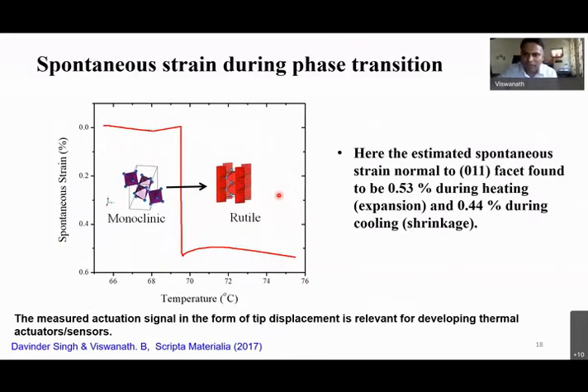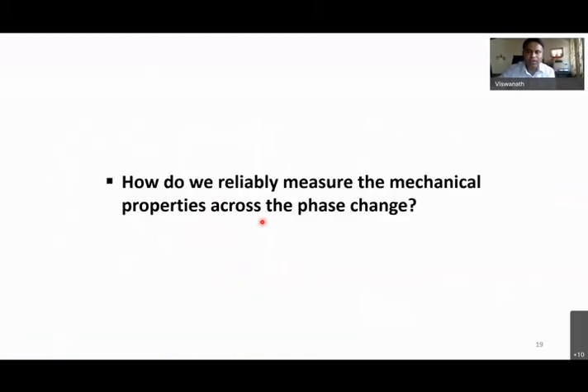Finally, we could find around 0.53% of spontaneous strain which can be reversibly tuned and can also be measured using nano indentation. In my opinion, when you have very small scales to deal with, actuation can be measured using TEM. If you have bulk material, in principle, we should be able to get reasonably accurate values using nano indentation. So the last piece of work, of course, I'll also show some more videos for the phase transformation of VO2.